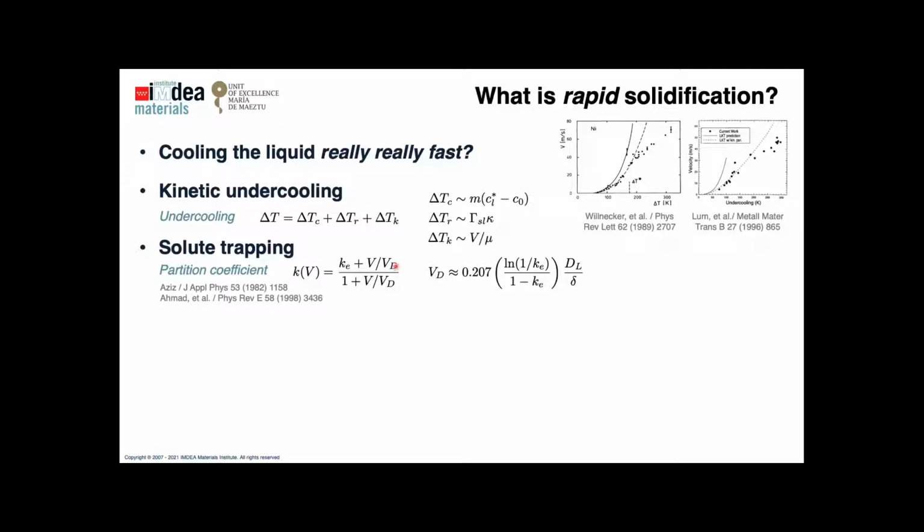That's a little bit of an obscure concept, but there are in the literature some definitions of how you can estimate it, or often it's just estimated as the diffusivity over the width of your interface, so a few atomic planes, right? And here you see that when the velocity goes to low values, when it's negligible versus this VD,